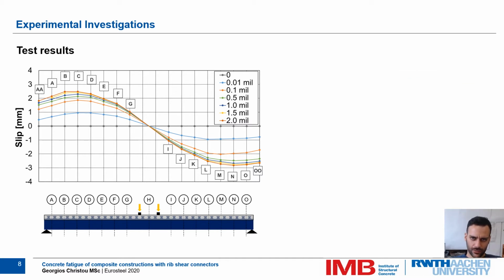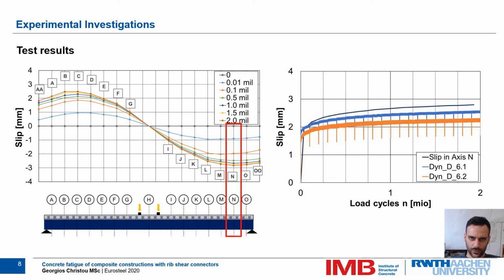Comparing the slip of the girder with the slip of a single push-out test, we can observe very similar results in case of the most loaded dowels of the girder. The slightly higher slip, which is reached in the dowel of the girder, can be led back to our simplified load determination in which we assumed an equally distributed shear force over all dowels within the shear fields of the girder. The force per dowel is actually affine to the slip in the interconnection, which leads to unevenly distributed shear forces in each dowel of the girder, at least in the beginning, before the occurrence of high inelastic slips.